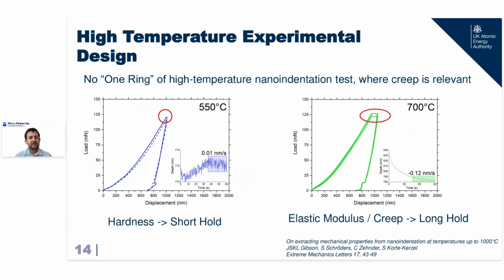But really, the takeaway from these tests is that there's no one ring to rule them all of high temperature nano indentation testing. I'm calling high temperature nano indentation testing where creep has a significant influence on the mechanical properties that you measure. You're stuck between deciding whether, at least if you're doing one test, hardness is more important for you, in which case you need to be doing a very short hold at peak, or whether you'd like to have a long creep hold period at that peak load, let that creep dissipate, measure it, understand it, and then have more accurate elastic modulus measurements.